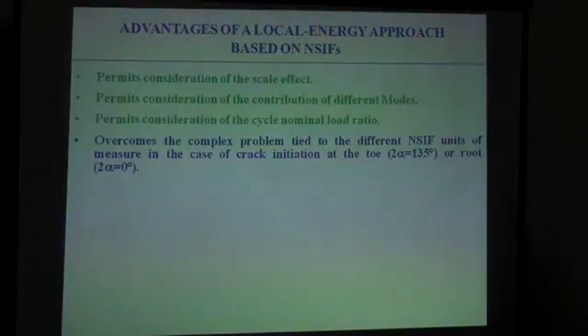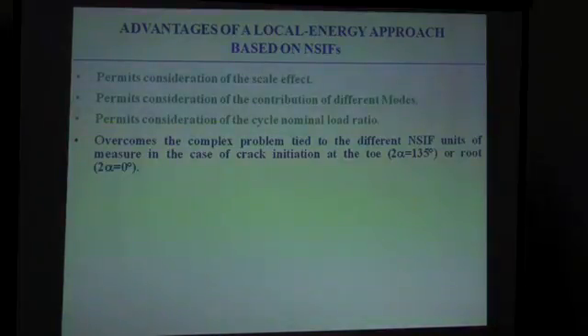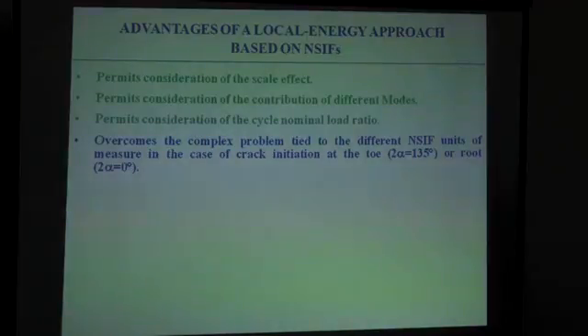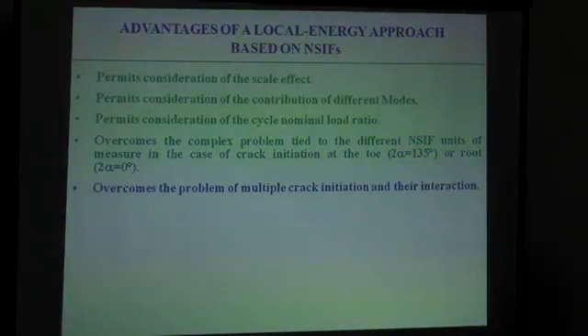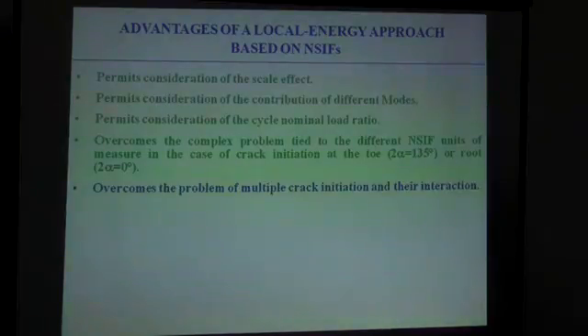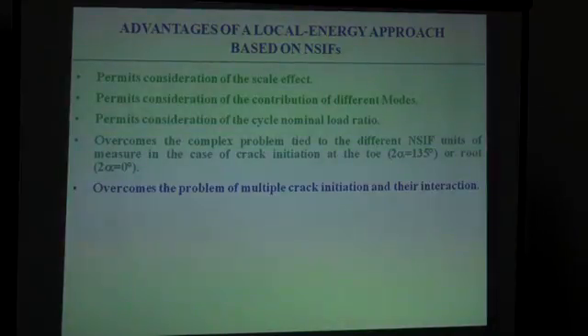And in some cases overcome the complex problems tied to different notch stress intensity factor units when we are comparing toe initiation or root initiation, for example, when we are considering welded joints, but also this is valid when we are comparing different kinds of notches. And in some cases overcomes the complex problem of multi-crack initiation and their interaction. This sentence is valid only if we are thinking of a criterion for the fatigue assessment, not if we want to study the path propagation of the cracks.